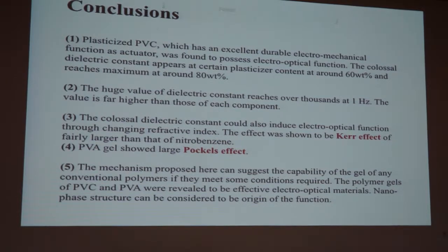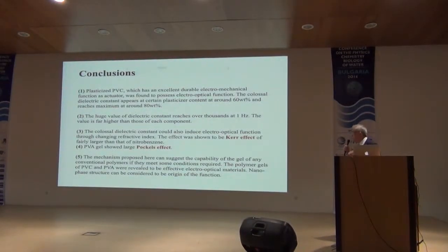So, summarizing my talk, the Kerr effect and Pockels effect are observed because of the large dielectric constant induced in the polymer gel from the interaction between polymer chain and plasticizer. And the interaction between polymer chain and plasticizer depends on the structure of the polymer gel, of course, and plasticizer. When changed from liquid to solid, the process is totally different, a big difference.